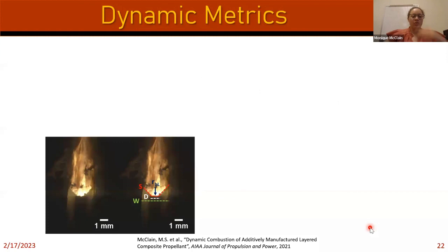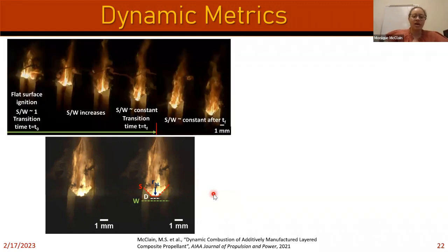And then, kind of quickly, we did try to define some new metrics. Based on the high-speed image data, we defined something called surface length. We're really trying to understand how the surface is evolving over time. We also measured the thickness of that middle layer, which is D, and W would be the thickness of the entire strand. Based on that, we tried to figure out how this evolves over time. When something ignites, the surface length and the width are relatively flat, so S over W is close to 1. But over time, you can see that surface length will increase. But then at some point, it stabilizes, right?